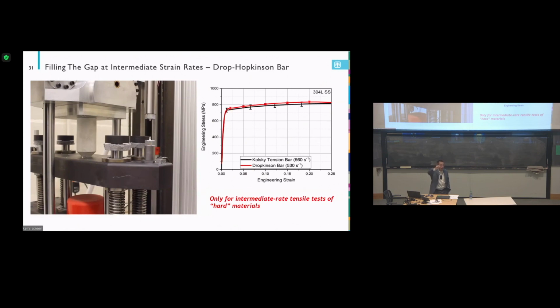Usually a Hopkinson bar can do as low as 500 per second strain rate. But this one maybe can further drop to about 100. But it's still difficult to drop below 100. So in that case, we collaborate with San Diego, California. We use a fast MTS. They call it high rate MTS. They may just move the strain rate up to 100. So this one can go as low as 100. So we fully close the gap. So problem solved, but only for tension.